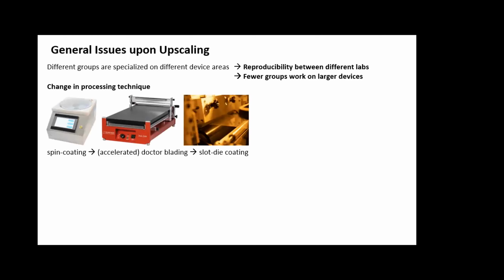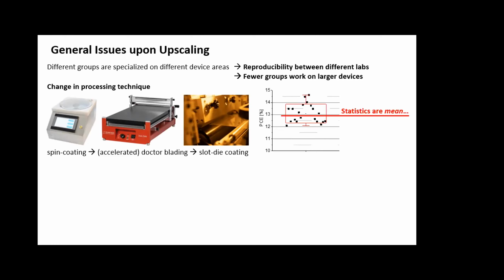This is an obvious thing everybody knows about. The small cells are made with a spin coater. For the larger ones, you need a doctor blade. If it gets even larger, you need to accelerate it, or you need a slot die coater. That's a change in process, which, especially when comparing spin coating and doctor blading, is a big change in the film formation process.